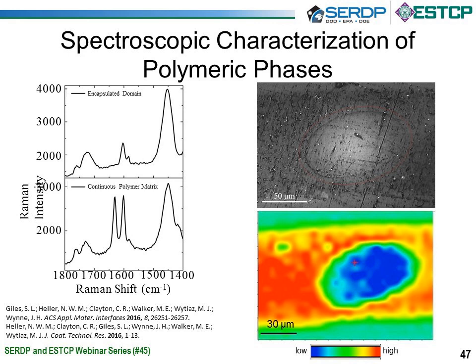In order to do so, we cross-sectioned the coating, embedded it in a resin system, and polished it for Raman analysis. The image in the upper right-hand screen is an optical image of a 150 micron thick film that has been sectioned and polished. You can see that within that red circle, there is a visible domain within a continuous phase of polymer.